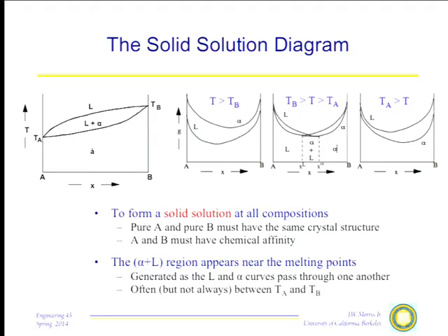Go to zero temperature, it's still a solid solution. Every solid solution that's out there, if you go to low enough temperature and if you give it a chance, it's got to either order or separate into two components. It's got to do something to get rid of the solution and satisfy the third law.